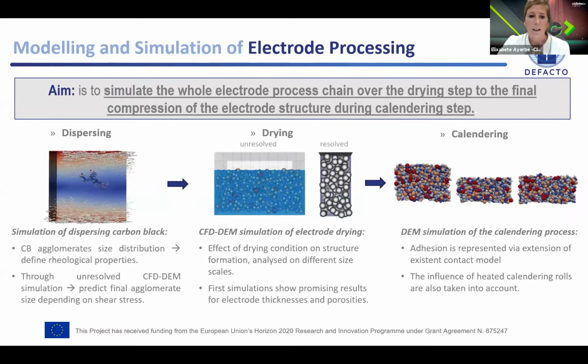Within the project, our colleagues have developed and resolved a CFD-DEM simulation, and through this simulation, I'm able to predict the final agglomerate size distribution depending on the shear stress. Now, coming to the drying step and considering this agglomerate size distribution, we can implement CFD-DEM simulation in both scales and resolve it. And we are able to track the evolution of the electrode thickness and porosity, depending on the mass loading.